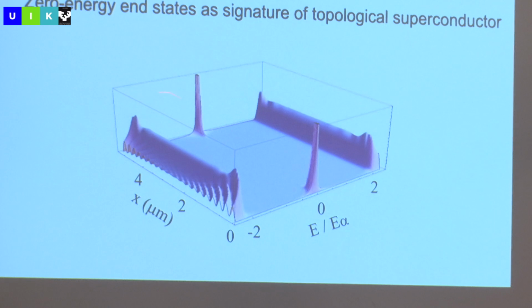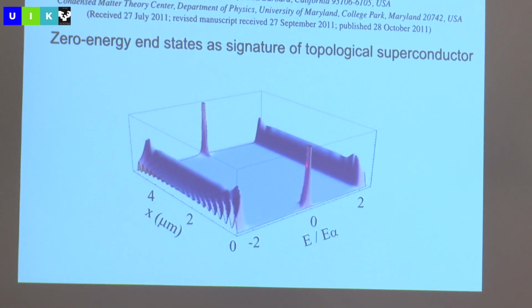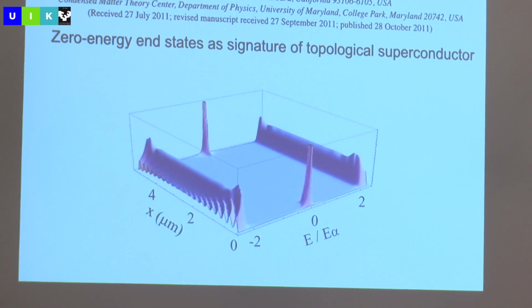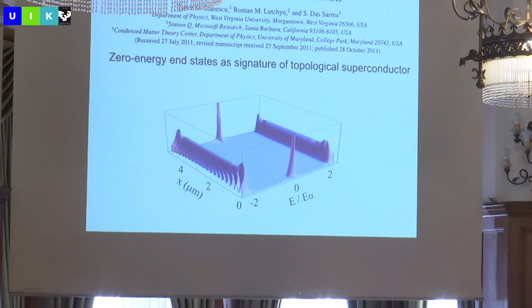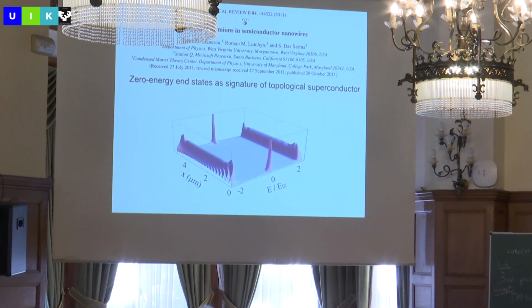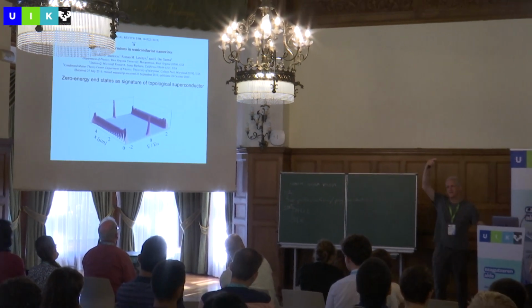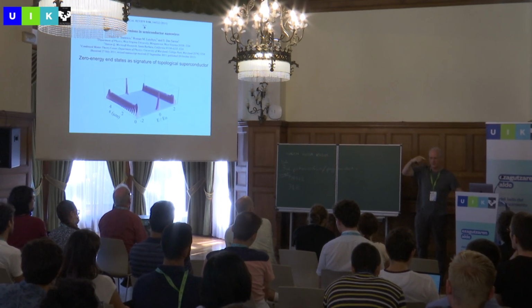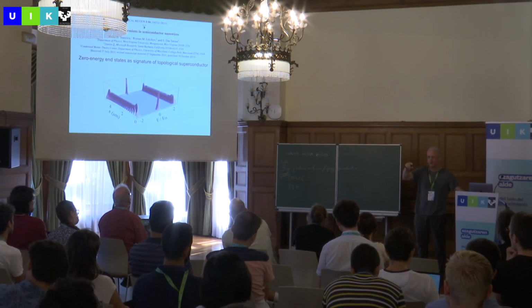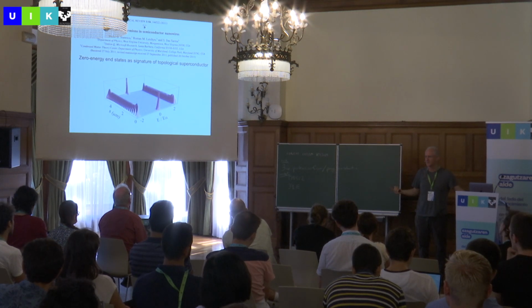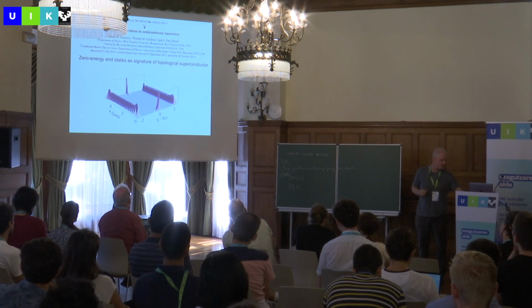But if you inject electrons into the ends of the wire, there will be a density of states for normal electrons just at the ends. So if you can tunnel into the ends of the wires, you'll see that electrons will go in, if there are Majoranas at the ends. If there aren't, it's difficult to tunnel in. You get high resistance when you try to tunnel into the end of a wire. Of course, you can tunnel in above the superconducting gap. But if you try to tunnel in at low energy, below the gap, nothing will go in and you'll get high resistance, unless there's something living at zero energy that lets you tunnel in.